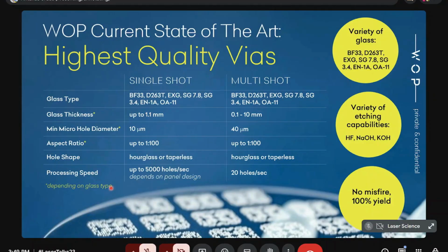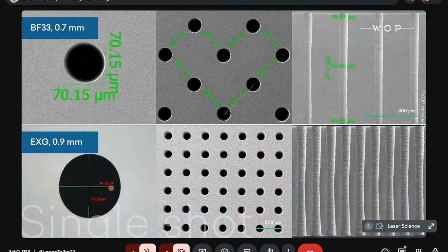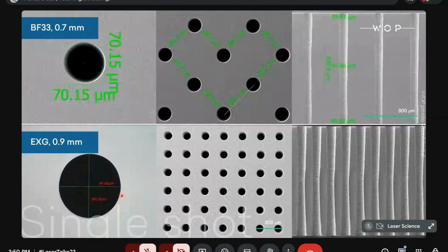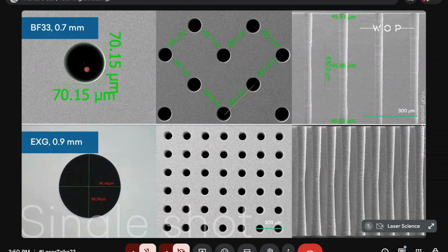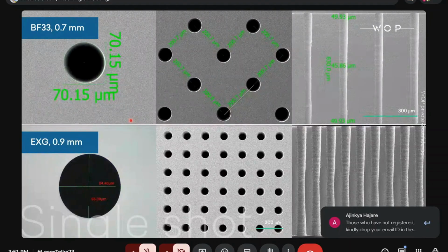You can see the parameters that we can provide. And here are some examples of how these vias can look. BF33 Borofloat is, I think, the best glass for making vias. You can see a very regular shape, very uniform along the depth. EXG aluminosilicate non-alkali glass is not so nice. If you see the cross section of the via, it is a little bit elliptical, more sensitive, and it is very hard to get roundness of 98%. Here it is, let's say, 100%. But it is such a hard glass, but we can handle it as well.